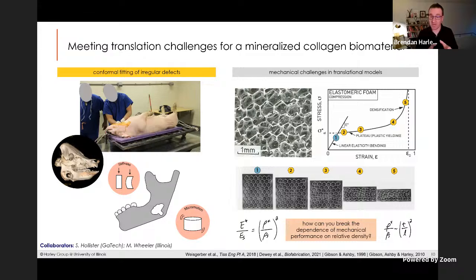Now, you put load on a material, and when you load it, it deforms. And so strain is a measure of deformation, where it's unitless. So the way you calculate strain is you say, how much did the material deform relative to how big it was? So if you take a piece of taffy, for example, that is 10 inches long and pull it to 11 inches, you've deformed it by 1 inch relative to 10 inches. So it's 10% strain. So as you go to higher levels of deformation, you have higher amounts of stress on your material. And so that's typically the way we think about mechanical performance.